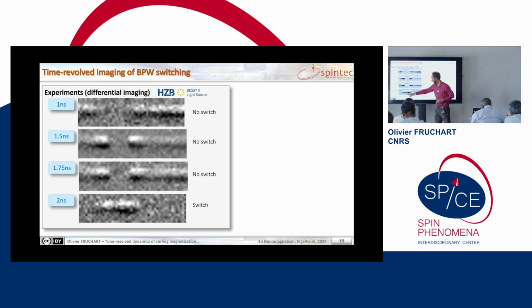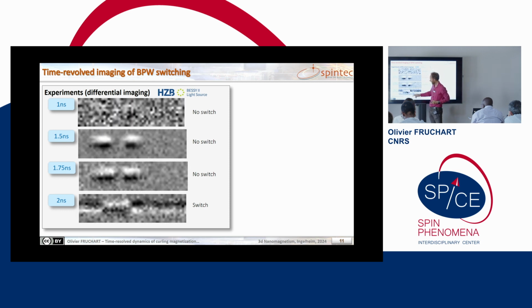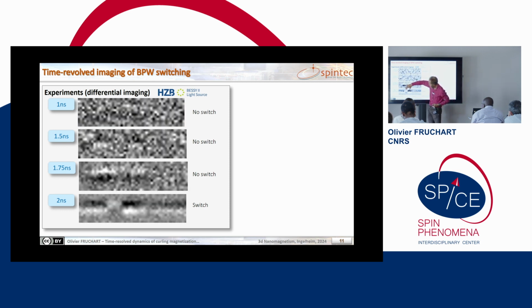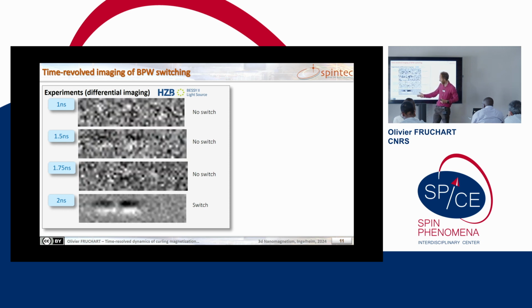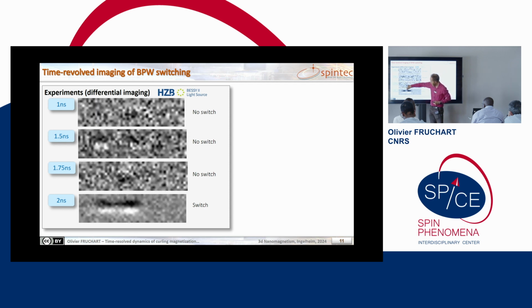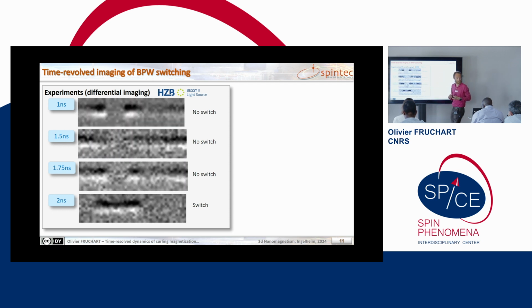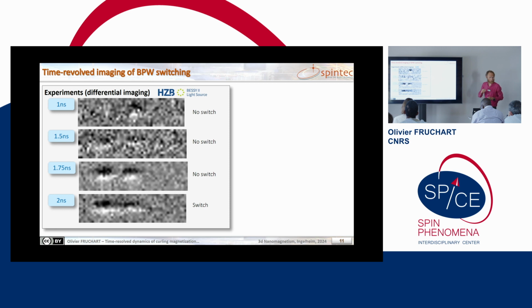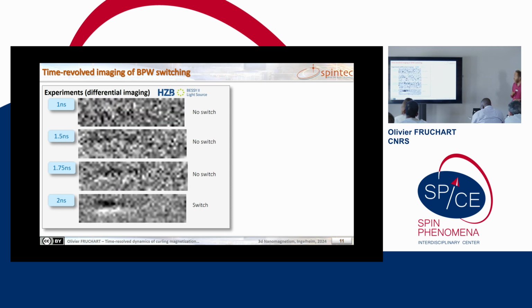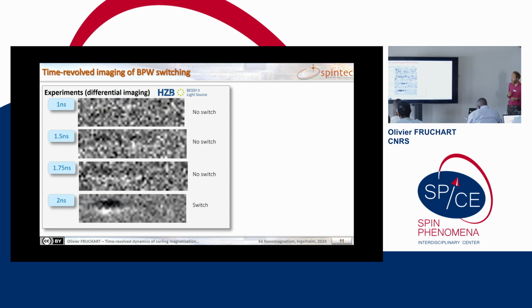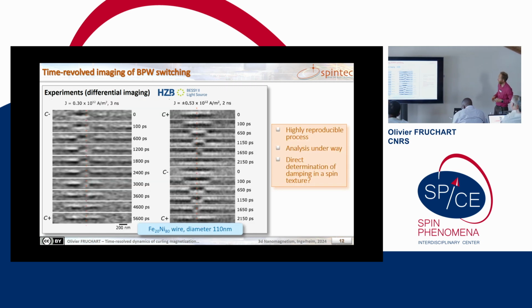But after a given threshold, in that case, it is 2 nanoseconds, in fact, the domain wall shrinks, okay, and it takes time even after you have stopped the pulse. And then it merges, and you have the final switching that I have shown previously. Okay, so we do not resolve this vortex anti-vortex. Probably it is stochastic, but at least we access the time scale.